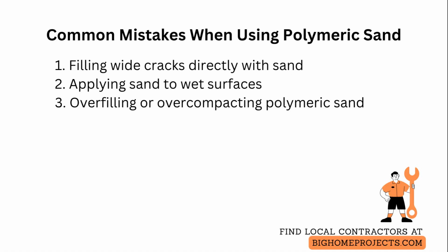Another frequent issue is applying polymeric sand to wet or dirty cracks, which prevents bonding. Clean and fully dry the crack before installation and wait for an extended dry window. People also pour polymeric sand too deep or over-compact it, which can cause poor curing and surface powdering. Follow the product depth guidelines and avoid tamping the sand down aggressively. Instead, use a gentle brooming and light compaction if recommended.